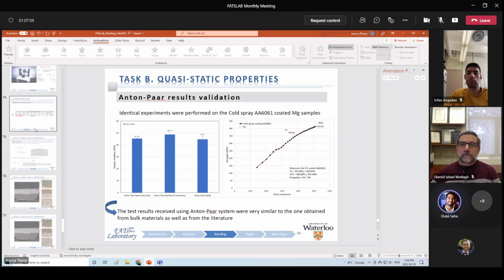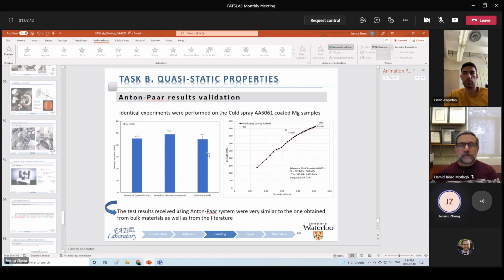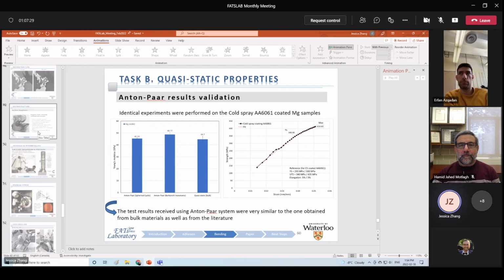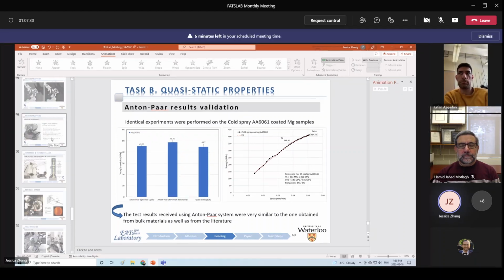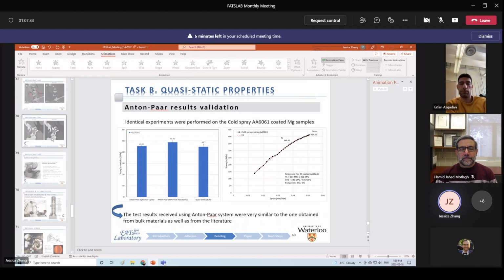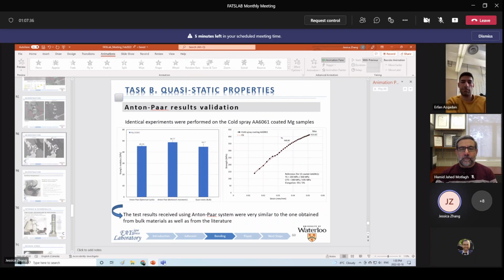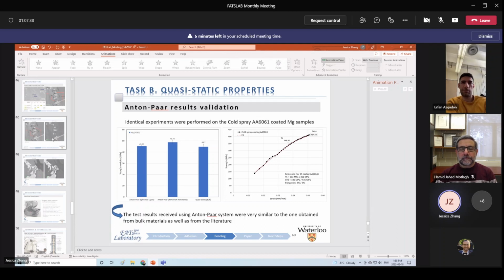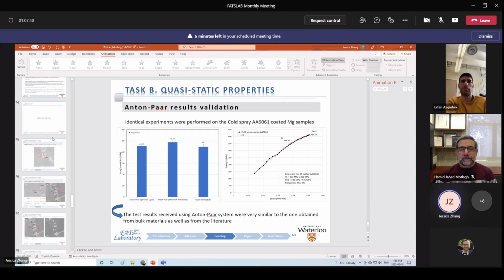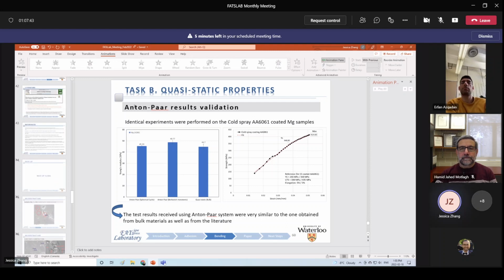Oh, and I wanted just to mention, as a fun fact, the reason we had to resort to Anton Paar is that we did try to use very small tensile samples of just the coating extracted from our samples. I think those samples were maybe 2 centimeters in length. And we went to the lab of a professor who does tensile tests on bone specimens. We did try to test that out, but the coating-only samples were very fragile. If you placed it on the table incorrectly, it would break. So that's why we had to resort.